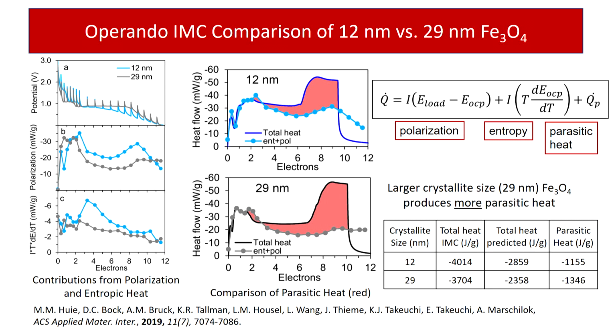By taking into account polarization and entropic contributions, we can model those, and for the first 2 electrons predict very well how the battery should behave in terms of the heat generation. But it's at about 2 electrons where we see deviation, where the total heat is larger than we can account for based on polarization and entropy, thus a parasitic reaction.